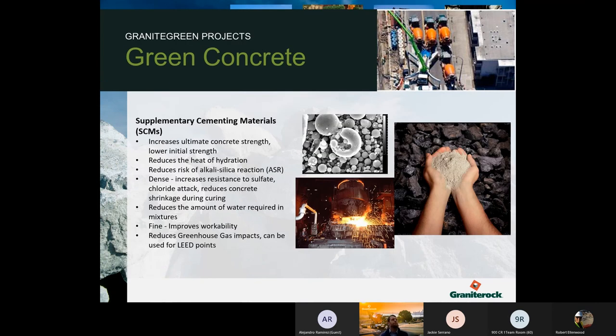So talking a bit more about SCMs, they increase ultimate strength while they can lower initial strength. The reason for this is you take out cement and say you put back fly ash, the only thing working to get the initial strength is the cement. So because you have a reduced amount, you'll have a lower strength up front. But the fly ash, when it combines with the byproducts from the hydraulic reaction, will make up that strength later on. Because you're taking out cement, it does reduce the heat of hydration, which can be helpful.